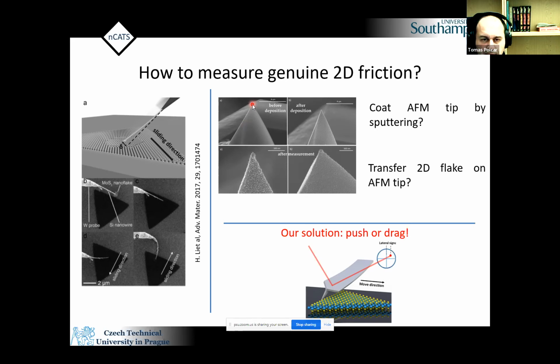You can try to sputter a very thin 2-3 nanometer layer and then crystallize it. We tried that. I would say it's very difficult, because it's difficult to analyze what you actually end up with on this tip. You can try to take a 2D flake and transfer it to the tip, but it's very difficult either, because the sharp tips have like 10, 20 nanometers diameter, so it's not easy to do.